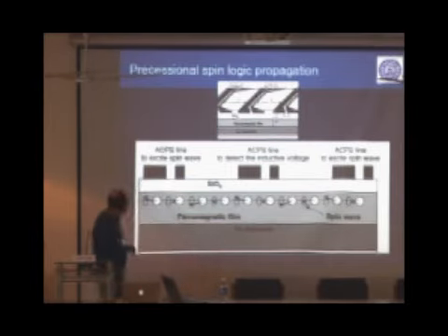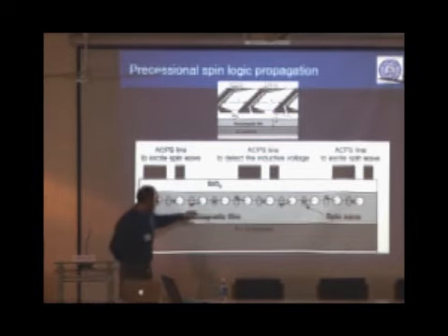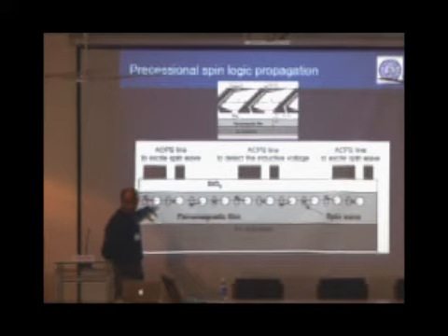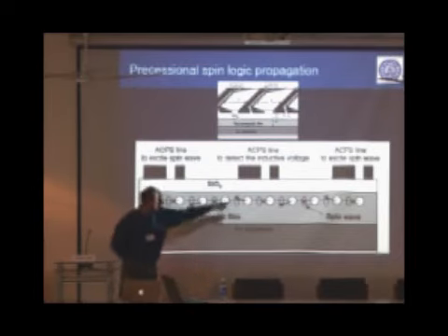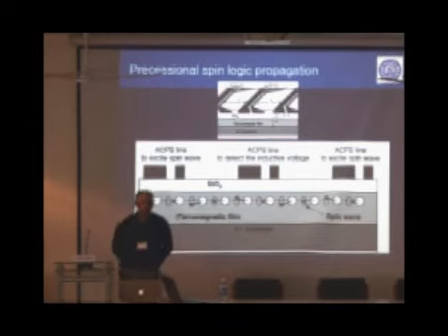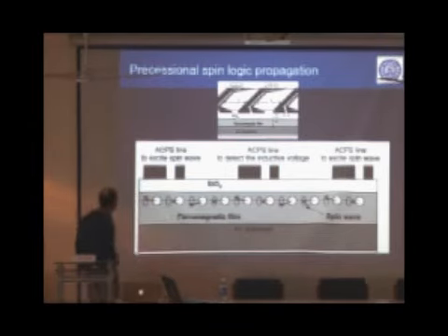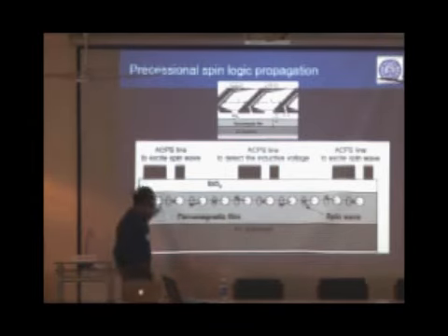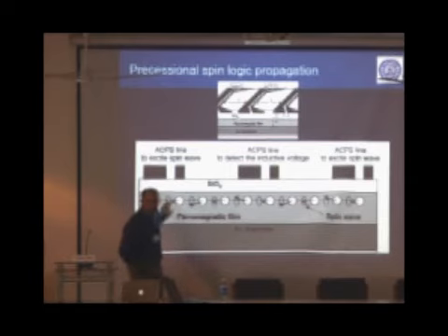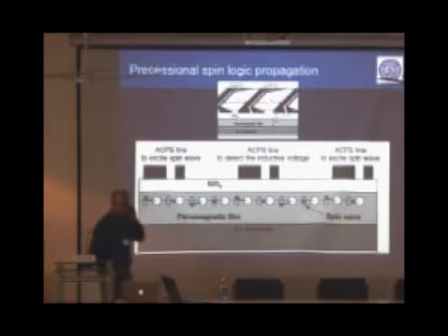And what essentially happens is, if you have a ferromagnetic film and you apply a very high tuned field, a pulse on one side, it launches a spin wave which causes precessional switching along the ferromagnetic film. What we will eventually do is replace this film with a layer of nanowires. But today I'll just show you some basic results on how switching happens in such a very thin layer of ferromagnet.